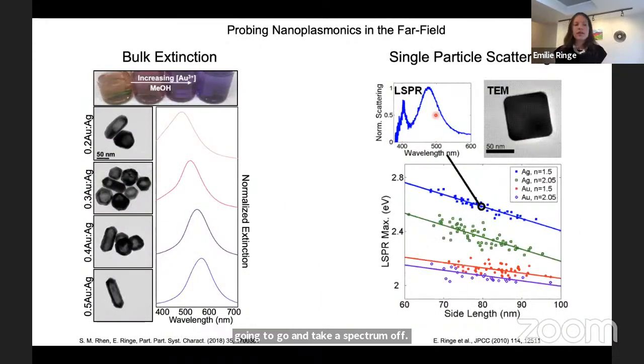So doing these kinds of techniques, for our UV-vis we get a bulk extinction, which is an ensemble average. Or on the right, if we do single particle scattering, we get information about the scattering from a single particle. That can be correlated with structural analysis, such as TEM, SEM, and so on, really teasing out information beyond the bulk averaging.